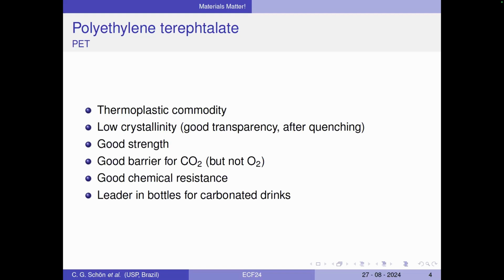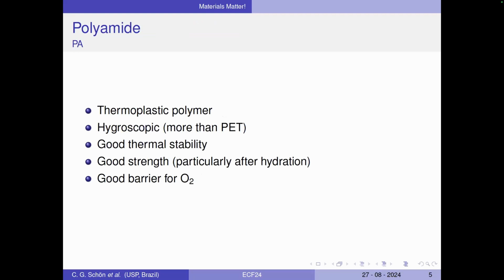Why PET? I don't need to remind you of all this. The important thing is that it is good for CO2 and not for oxygen. So it's not a good idea to place things that will get bad with time with PET. PA has a better performance in this, but has also biggest problems, and this is why we are doing blends. The idea is, of course, is it compatible? We had no idea before starting this.